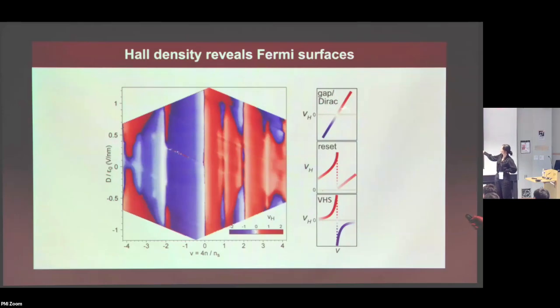The first one is gap or Dirac-like behavior, where, as you increase the doping level, your Hall density just linearly crosses zero and changes the polarity, changes the sign. So the hole-like carrier turned into an electron-like carrier. That's a very simple gap or Dirac cone-like behavior. And this is happening at the charge neutrality point, where it's supposed to happen.